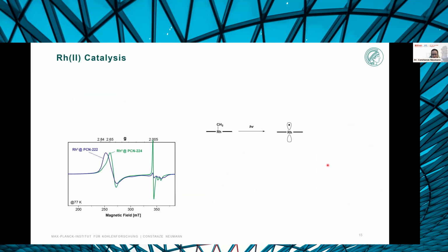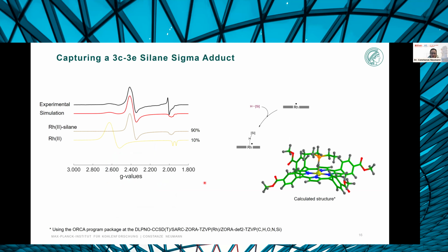And EPR was very helpful in that context because we could readily confirm that upon photolysis of the rhodium-carbon bond, we in fact get these site-isolated rhodium-2 metalloradicals. And we see that the breadth of the EPR signal changes significantly for the two MOFs because the distance between the two rhodium centers is varied as we go from one MOF framework to the next, so that we can modulate the electronic communication between those two centers.